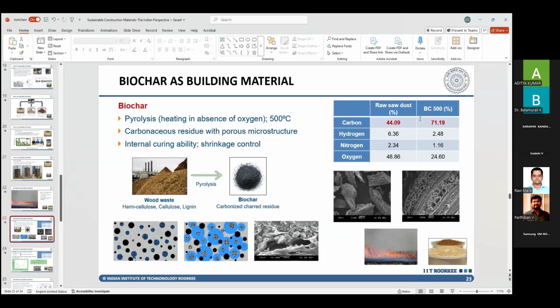So if you look at your table on the right top, this was another study that we did, raw sawdust, where we had about 44% carbon content, elemental carbon. The moment we pyrolyzed it at 500 degrees centigrade, heated it at 500 degrees centigrade without oxygen, without air, the char that we obtained was more than 70% carbon. So essentially, all this carbon which would have gone to the atmosphere, you have saved and you have kept it inside.